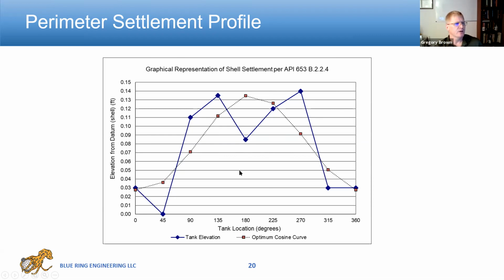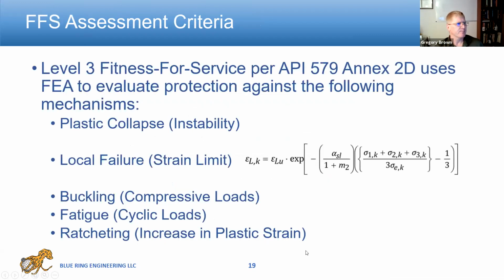And then you can actually use those measurements in API 653. The tank code, it did not meet those requirements, so we did a final analysis with, or sorry, with 579. Now, when we do a level 3 analysis, there's various rules we have to meet. We have to evaluate what's called plastic collapse or instability. What this is, the loads on the structure are so high that it overcomes the yield and tensile of the material. The entire material comes apart and causes failure. So there's a set of rules for plastic collapse. This is an instability in the structure.